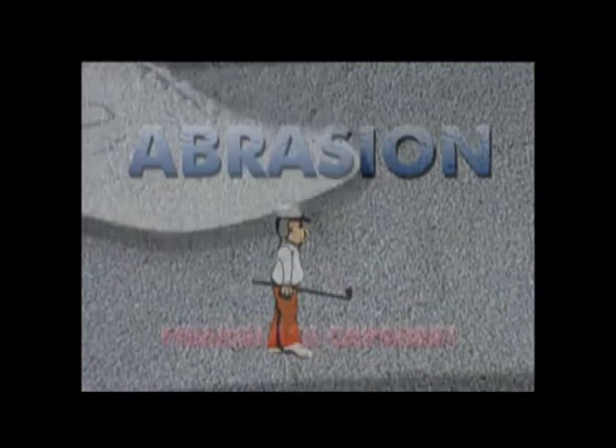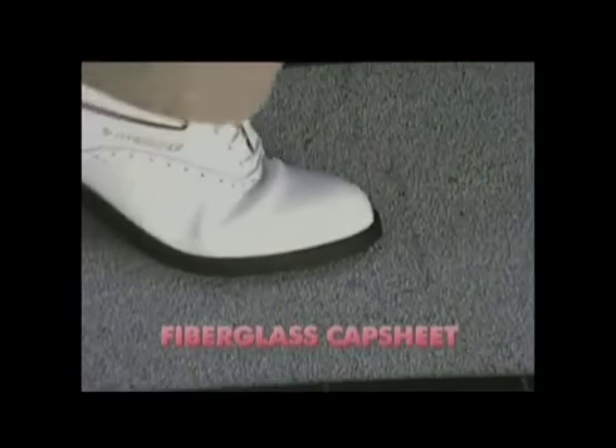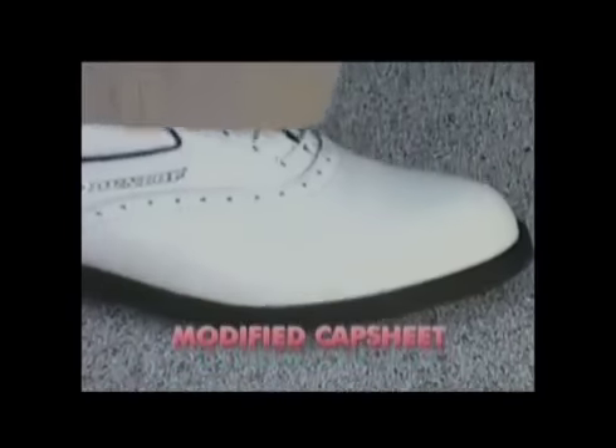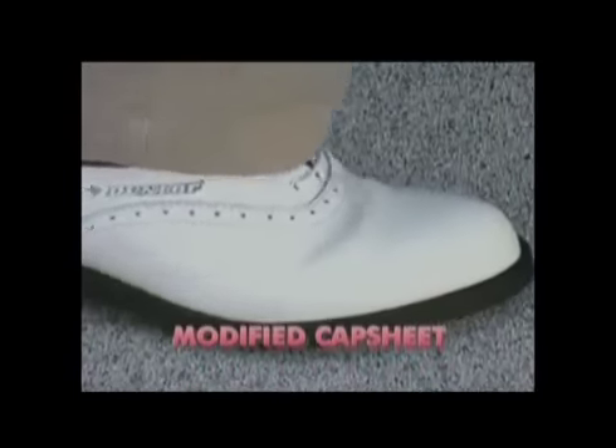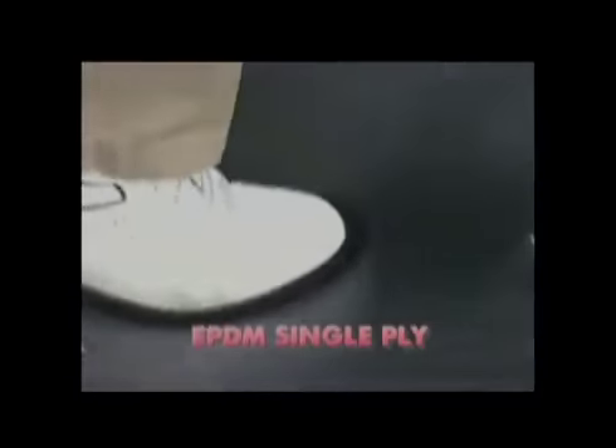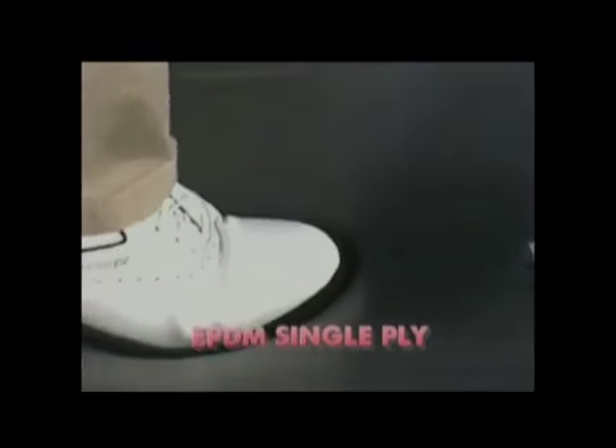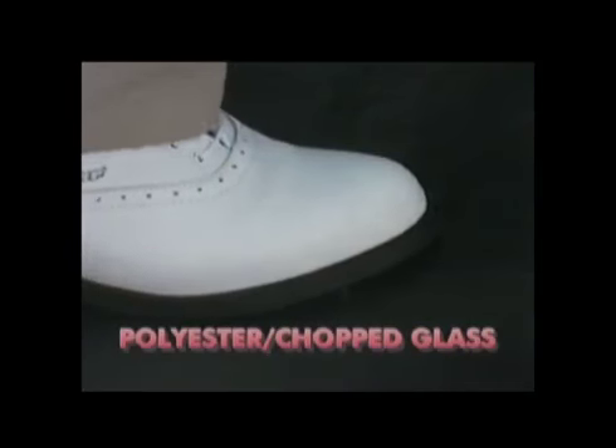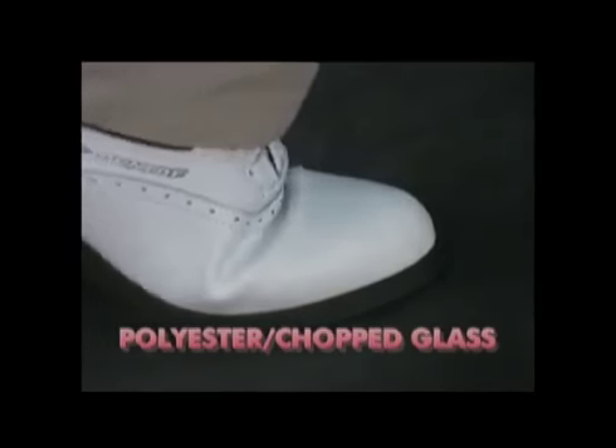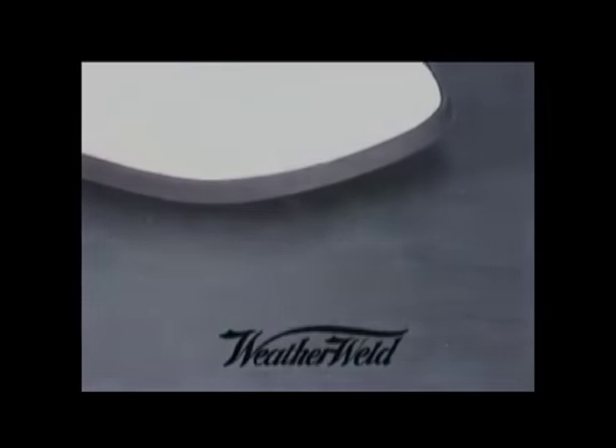Abrasion to a roof surface from rooftop traffic and mechanical changeouts is an inevitable problem. Granules can partially protect, but they can also hide damage. A screw on the bottom of the shoe can make major problems for a thin stretch-based single-ply or polyester system. Here, stretch without strength means pinpoint weakness. But WeatherWeld's fiberglass composite structure is strong enough to limit damage to only the surface.